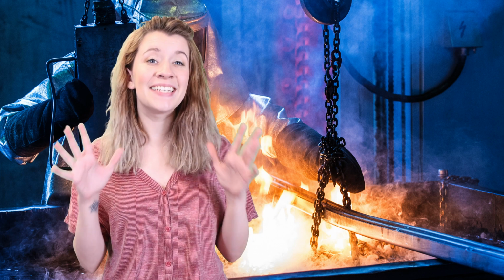At the end of the process, it is blasted with cool air in a process called quenching. This causes the outer layer to cool quicker than the inner layer, which causes tension within the glass, making it 10 times stronger. Because of the tension within tempered glass, it cannot be cut or drilled without shattering it entirely. That is why you need to cut it to the size you need before tempering it. Generally speaking, first surface mirrors are never supplied as tempered. This is because you need to apply the mirror coating before tempering, and then once it is tempered, it can cause distortion, which defeats the purpose of being an optically flat mirror.